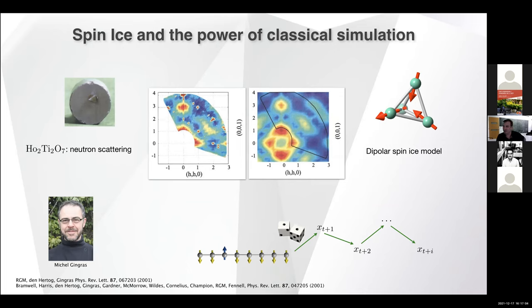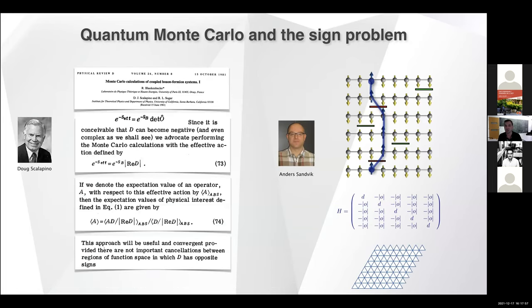A lot of the properties of spin ice were determined through neutron scattering. This is figures taken from some early paper I was involved with, that involved Tom Fennell and other neutron scatterers, who put a single crystal of holmium titanate in a beam and got this reciprocal space intensity pattern here. What Michel Gingras, Byron Den-Hertog, myself and others were looking at was the so-called dipolar spin ice model. It's really a microscopic model of the interactions occurring in holmium titanate. I've drawn a schematic of one of the units of the crystal lattice, which is a tetrahedron. The magnetic moments live on the corners of the tetrahedron.